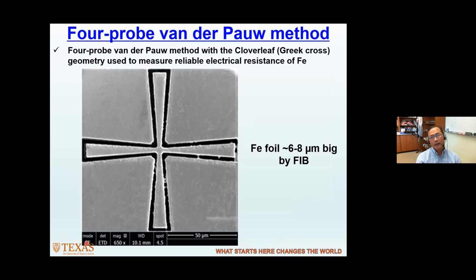So our approach was a bit different. We use a focused ion beam to prepare a small piece of sample iron that has the central grid of only about 6 to 8 micron. So that actually matches the size of the laser heating beam. So the idea here is to really follow the parameters in the van der Pauw method, that you need kind of a homogeneous sample. You can laser heat the whole sample, and the contact regions need to be as symmetric as possible, things like that.